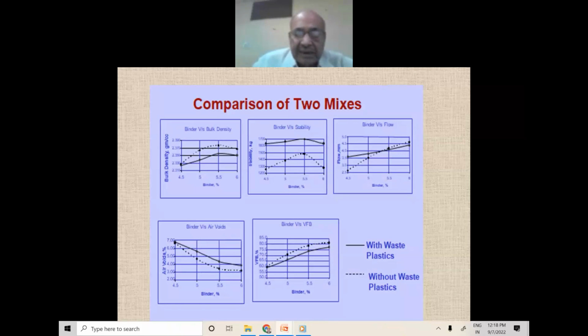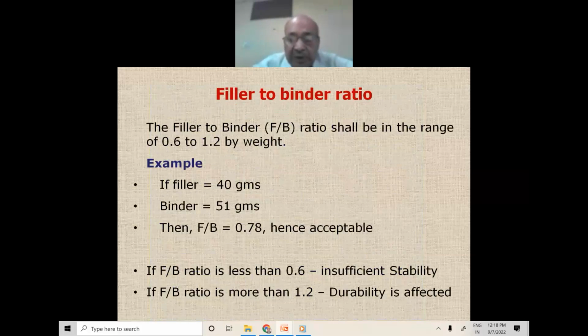After getting the optimum bitumen content, we will determine the optimum plastic content in the mix. Say the optimum bitumen content is 5.5%. We will prepare samples at optimum bitumen content, varying the plastic content: 5%, 6%, 7%, and 8% plastic content. And all the properties like stability, flow, voids, voids filled with bitumen, and voids in mineral aggregate shall be determined.